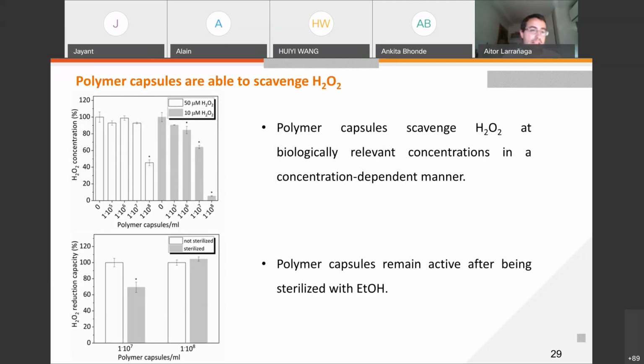So we repeated this exact experiment, but with polymer capsules that underwent a sterilization process with ethanol. We found that after the sterilization process with ethanol, the antioxidant capacity of the polymer capsules was almost the same, which suggests that these capsules are robust and they can undergo a sterilization process with ethanol prior to any in vitro or in vivo study.